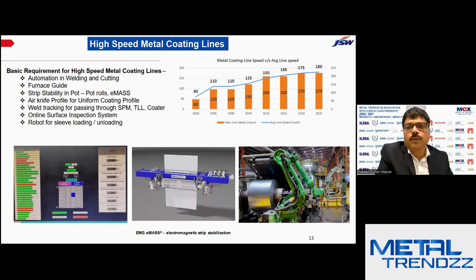So here you can see the high-speed metal coating lines, how it evolved from 1990 to 2025. You can see the maximum speed of the metal coating lines as well as average speed. So the major basic requirements for running any metal coating line at high speed is, key is automation, then strip stabilizing, because at high speed you have a lot of challenges controlling the zinc coating. So you must have a very stabilized strip coming out of the zinc pot. So eMASS is helping in that category, the electromagnetic strip stabilizer. Then you have a very better tracking of weld through skin pass, leveler and all.